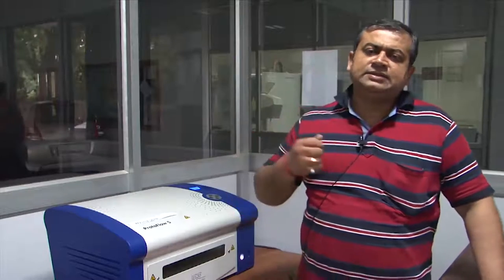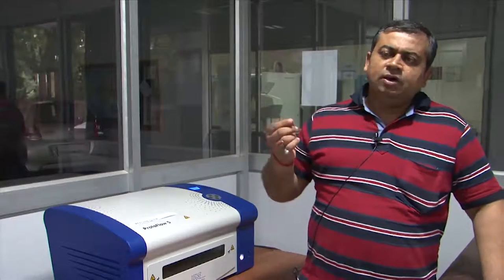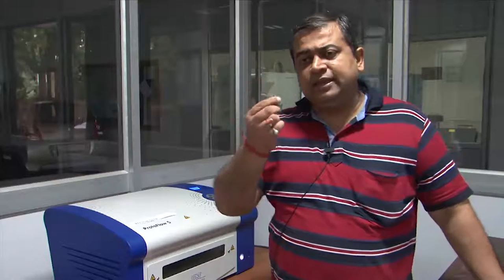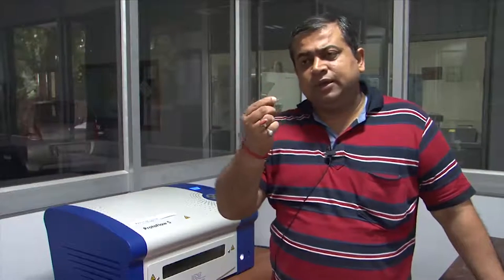So the first step, it's a programmable oven, as I told you, is to heat it for about 140 seconds at 190 degrees Celsius, so that it gets rid of all the air bubbles enclosed within the paste. The second step is to reflow it, and the reflow condition happens at 270 degrees, where typically the solder starts melting and goes around those places where the leads of the components, the input and output of the components, are placed.